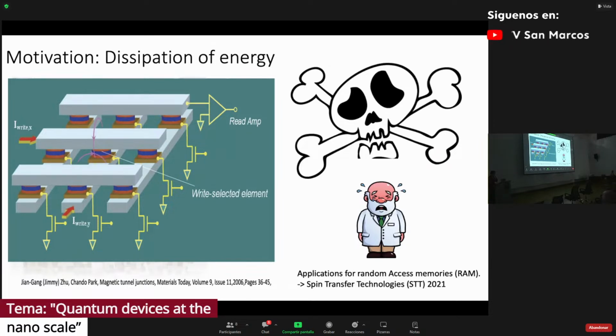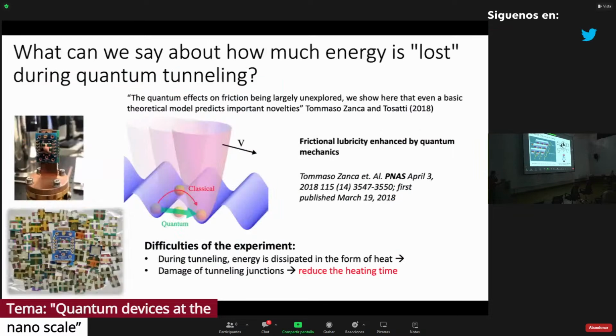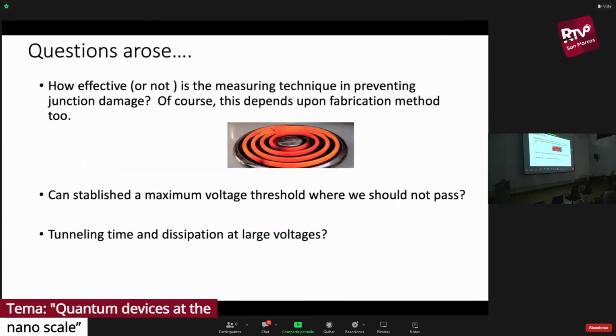So there have been a few people trying to study friction, quantum friction, and there's one quote from this paper from Tommaso, where it says the quantum effects on friction being largely unexplored. We show here that even a basic theoretical model predicts important novelties. So there is not so much on quantum friction. And the question is how effective or not is the measuring technique in preventing damage to the tunnel junction. If we can understand quantum friction, then the way we send the current can be modified in order to have less dissipation, or less heat, and also be able to thermalize this heat with the bath.